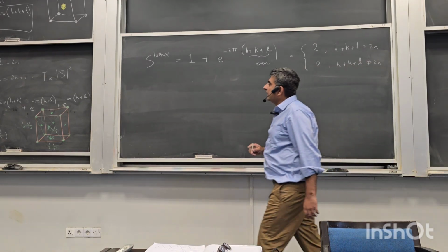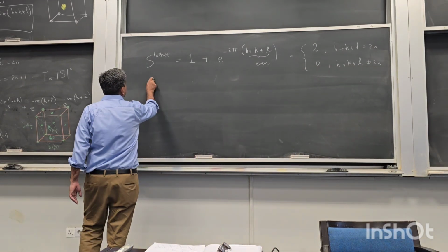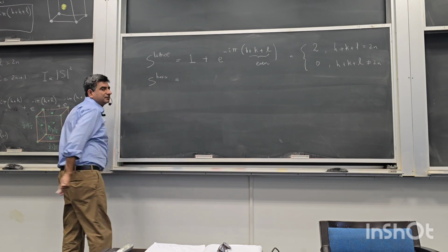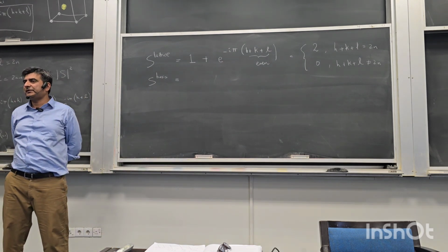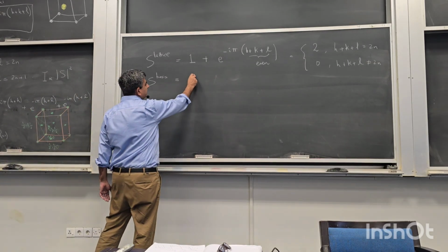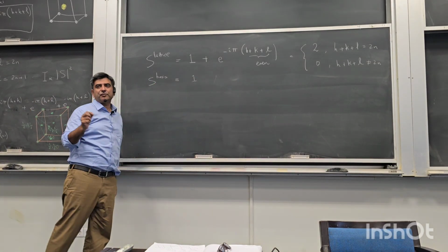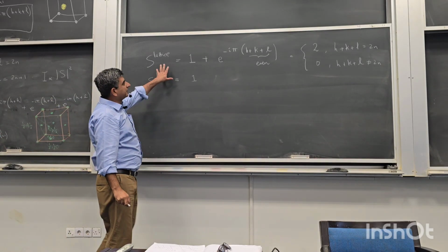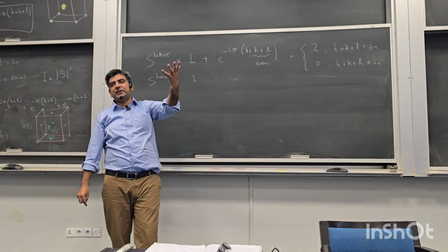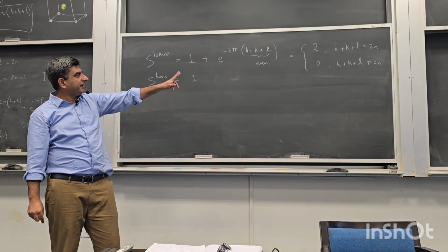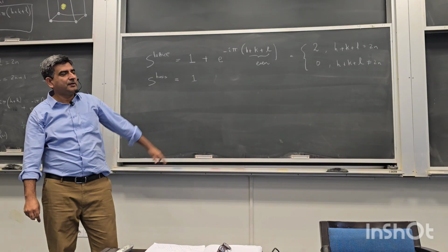Okay. So now let's look at the basis. What's the basis for iron, BCC iron? It's just a single atom, so this is going to be 1. That atom can be taken to be at 0, 0, 0. So the overall structure factor is simply arising from the lattice, and there is a systematic absence when H plus K plus L is odd.